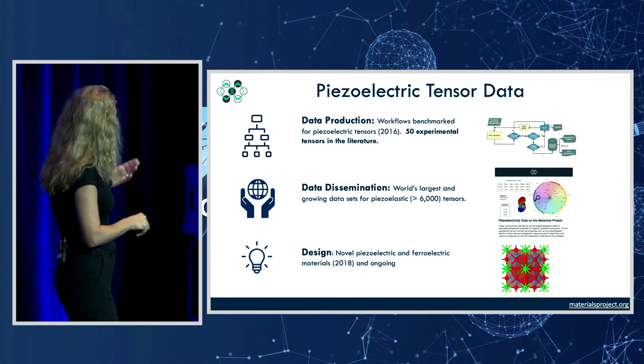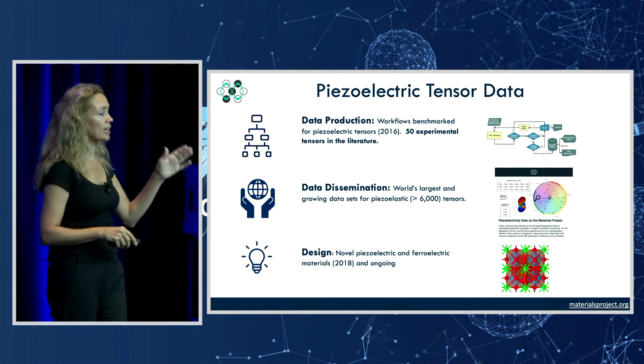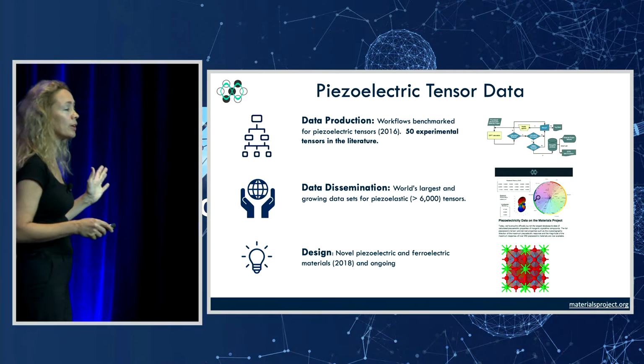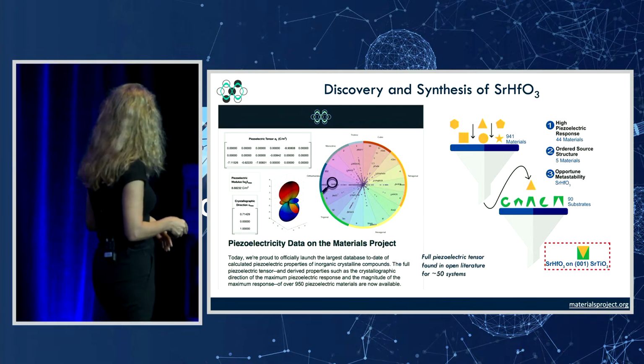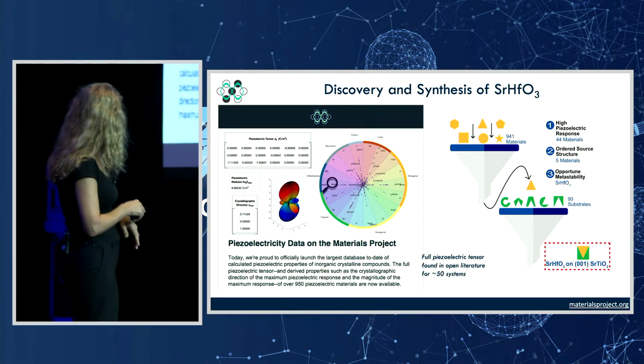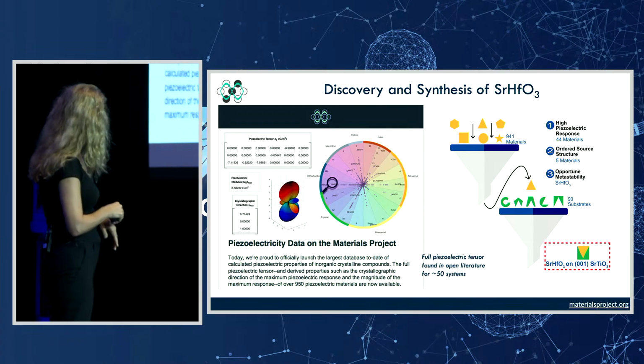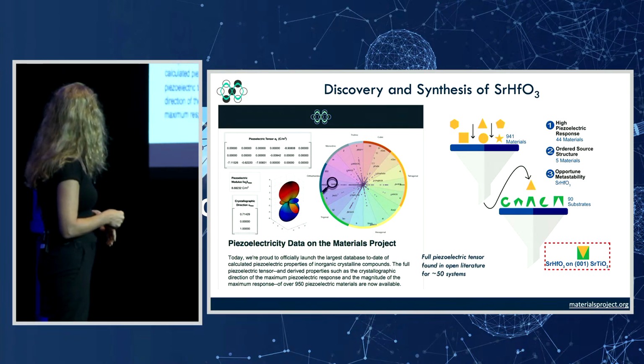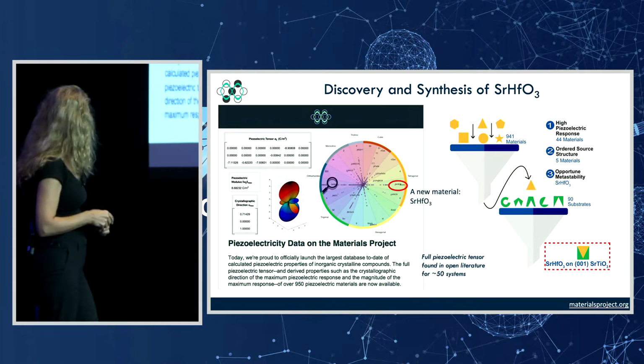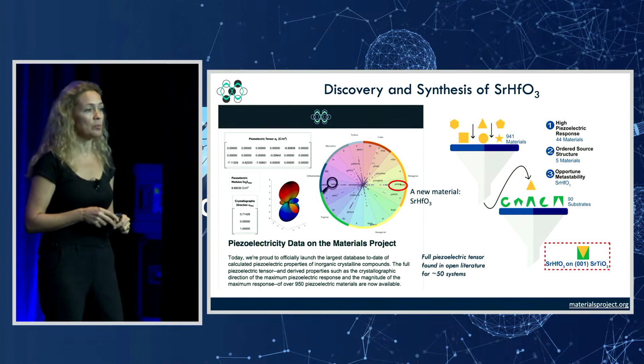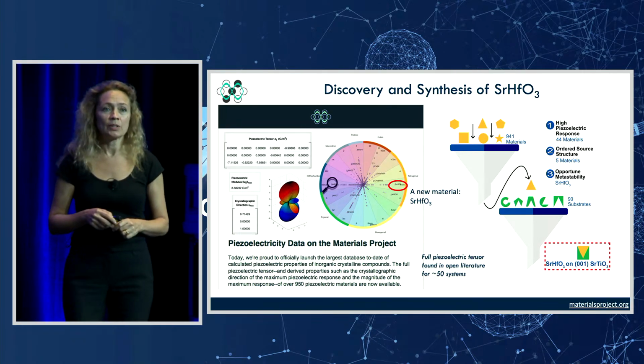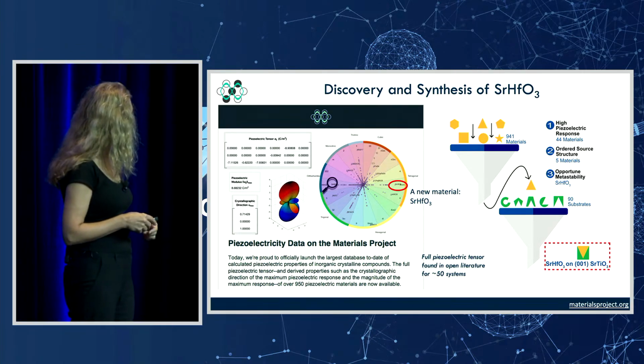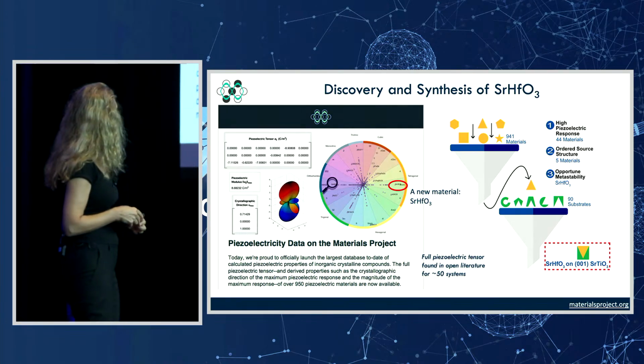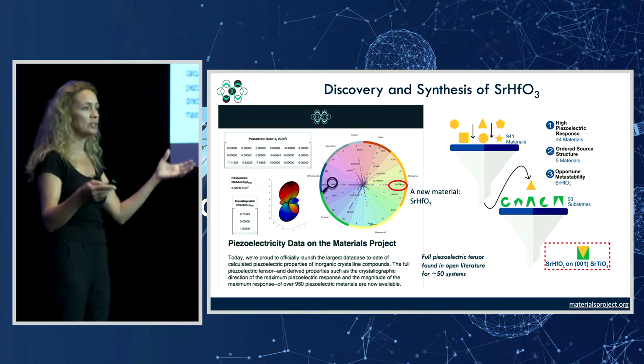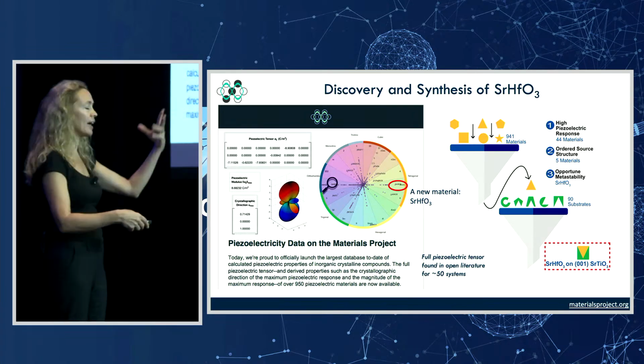In the early days, when we had about 1,000, we decided to filter and see which ones could be a candidate, maybe. This is the first data set that we had, and we filtered it just like we did for the photocatalytic material. We found an interesting material, we thought, a strontium hafnium oxide that had never been made before. It had a high piezoelectric response in one direction, and we thought, okay, maybe this is cool. So what do you do when you have a completely new material that falls out of the funnel and just has a high performance metric?